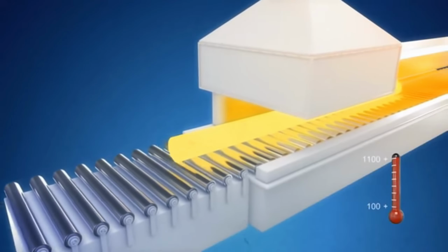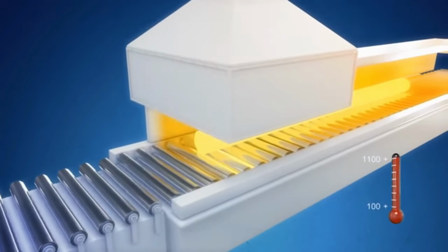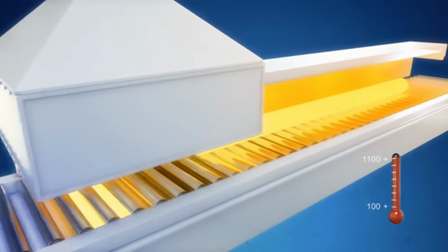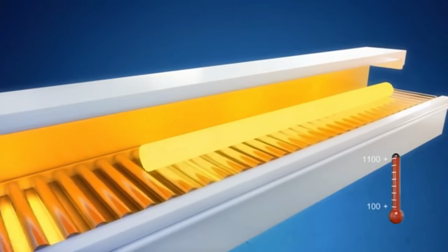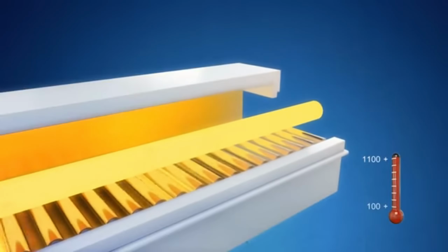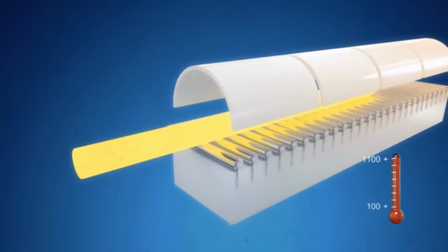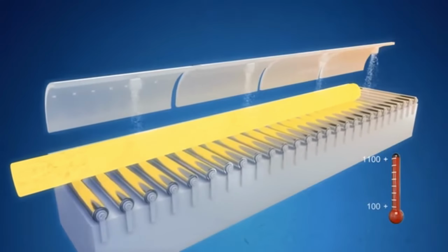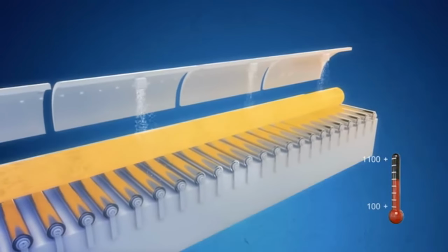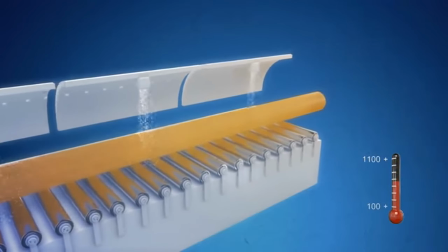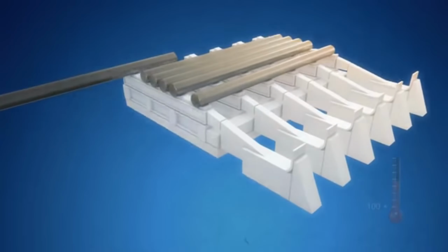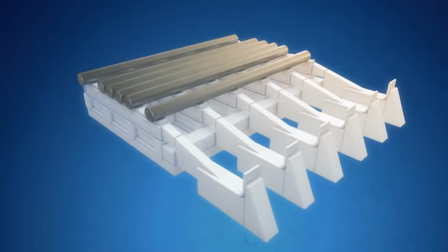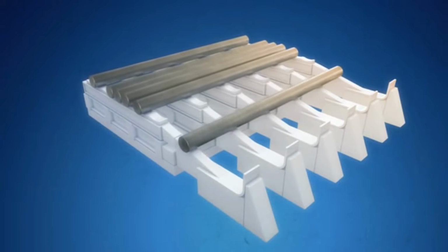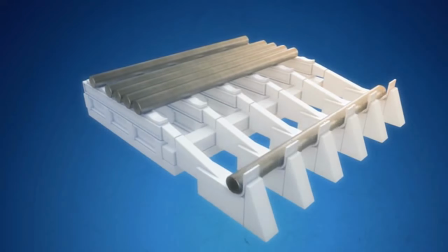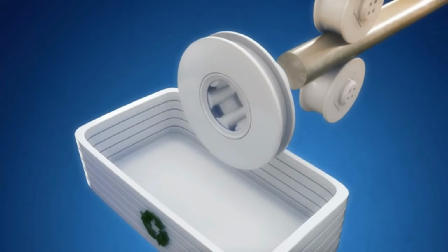The bar, now round, is reheated to 1260 degrees centigrade in a quench annealing furnace, followed by rapid cooling in water to ensure the material structure is in accordance with official international and customers' specifications. The bars are transported to the cooling bed, before being peel-turned and polished to mirror finish.